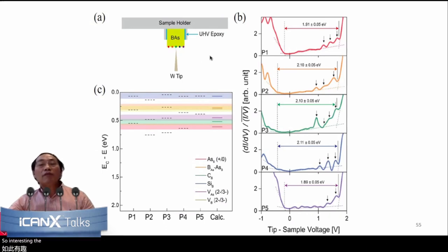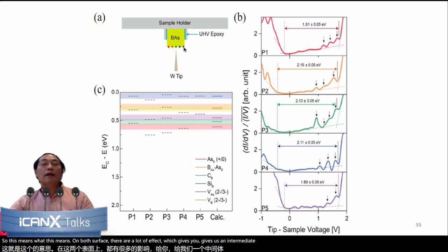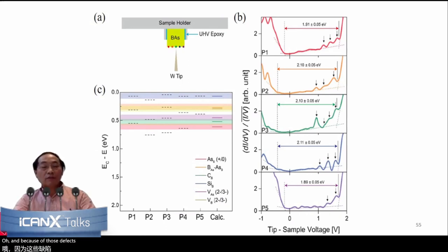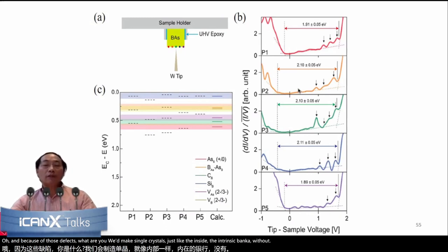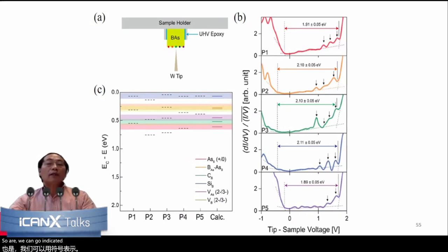So interestingly, what they found is that close to the surface, the band gap is about 1.9 eV. And going closer to the inside, it's over 2.1 eV, okay? And then on the other side it becomes about 1.9 eV again. So what does this mean? This means that on both surfaces there are lots of defects, which give us intermediate states. And because of those defects, what if we make single crystals just like the inside, with the intrinsic band gap and without defects? Are we going to get the mobility much higher than 1600? And are we also going to get the thermal conductivity much higher than the 1300 that we demonstrated so far? Which I believe we will.